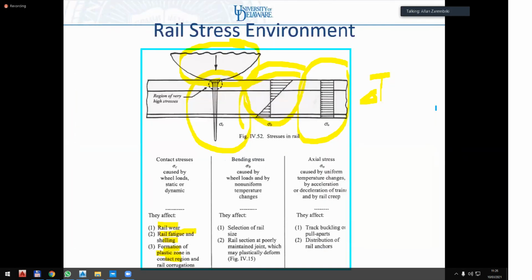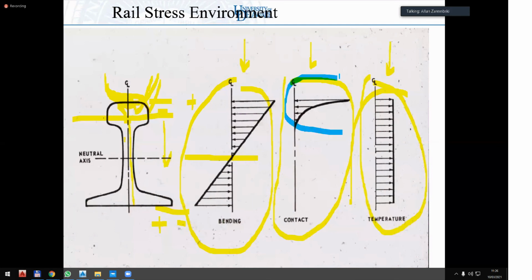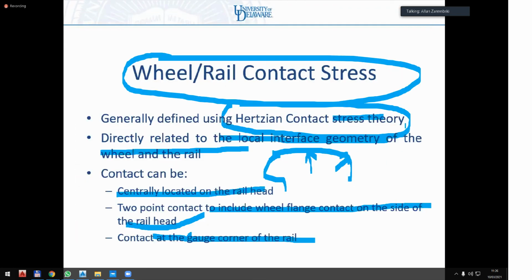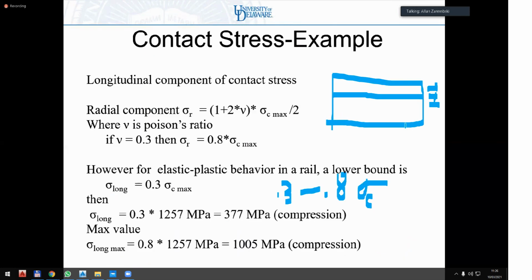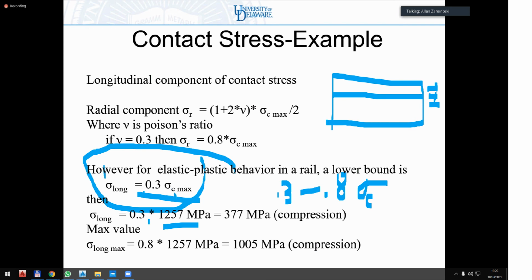So if I go back here, if I want to add this contact stress to my bending and my thermal stress, I need the longitudinal component. It's no longer the Hertzian contact stress, which now is in the down direction. My longitudinal component is between 0.3 and 0.8. For most elastic plastic behavior, it's about 0.3. So 0.3 sigma sub C max: if my stress is 1257 megapascals sigma sub C max, my longitudinal component of the contact stress is 377 megapascals.